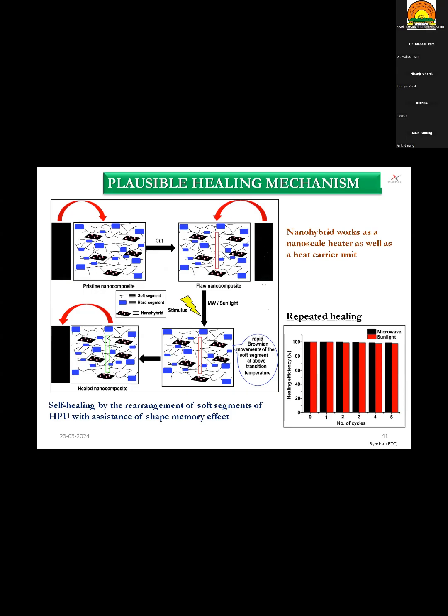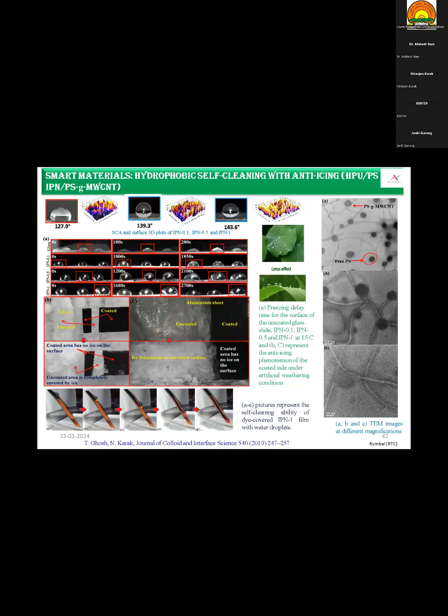So we have proposed a mechanism in our system: the nanomaterials that are used act as a nanoscale heater. When we apply this stimulus, whether it is microwave or sunlight, they absorb energy and dissipate it into the system. As a result, micro-Brownian movement of the soft, flexible segments starts, and they rapidly move forward to where there is damage and heal the surface. Thus, repeated healing is possible, unlike the externally added encapsulated self-healing agents.